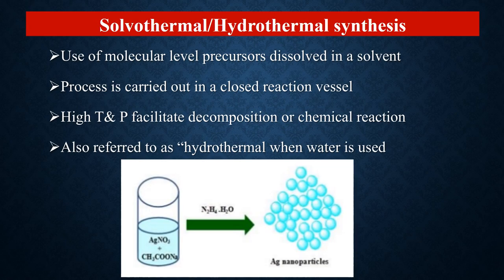There is solvothermal or hydrothermal synthesis. If some other solvent is used it is called solvothermal; if water is used as the solvent the process is known as hydrothermal synthesis. Molecular-level precursors are dissolved in the solvent and the reaction is carried out in a closed vessel at high temperature and pressure, where the precursor is decomposed by chemical reaction to produce the required nanoparticle. For example, silver nitrate in the presence of sodium acetate and hydrazine is converted into silver nanoparticles.